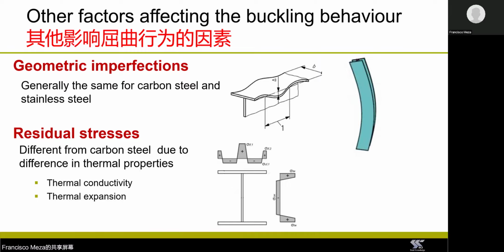Now, the residual stresses of stainless steel and carbon steel sections are generally different because of the different thermal properties of carbon steel and stainless steel, as Nancy showed you previously. The main thermal properties affecting the residual stresses are the thermal conductivity and the thermal expansion. So the thermal conductivity of stainless steel tends to be lower than for carbon steel, and the thermal expansion tends to be larger. And for austenitic stainless steel, the thermal conductivity is the lowest, and the thermal expansion is the largest. And they also show the most pronounced loss of stiffness, and because of that, they tend to exhibit the lowest buckling performance of all the stainless steel alloy families.